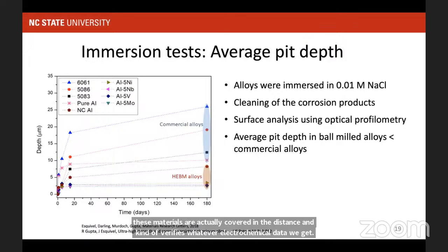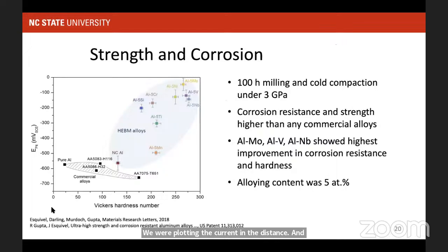Now, putting this data, this corrosion resistance, as a function of the strength. You remember the graph I showed you in the beginning. We were plotting the corrosion resistance as a function of the strength, right? Here our commercial alloys are pure aluminum and high strength aluminum alloys. And what we did is, the alloys we made here, we actually reached this top right corner. So we have alloys which have about a gigapascal of yield strength and very high corrosion resistance. So that's all good.